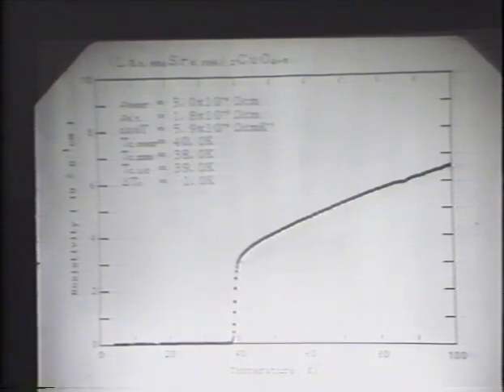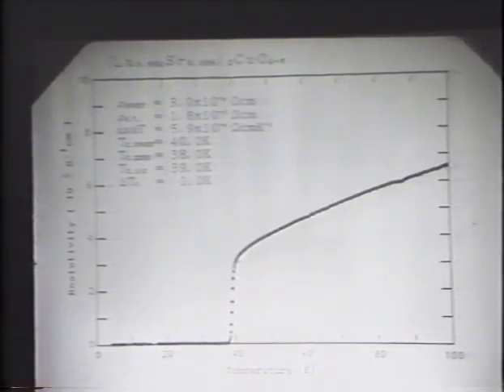We used high quality samples. High quality means a large Meissner effect and a very sharp drop of resistivity. The transition range is less than 1 degree Kelvin, as is shown in this graph. Time is not enough, so I only show you the results of our experiments. We measured mainly the dependence of many physical quantities on the concentration of barium or strontium.